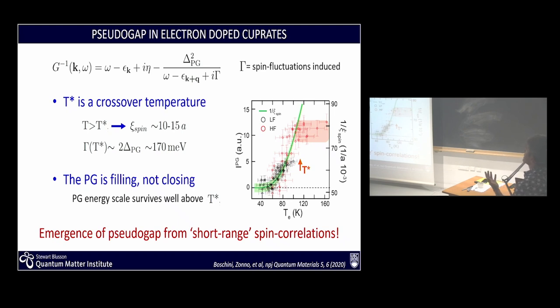We can also fit, as we did before, the photoemission intensity using a spectral function, or a Green's function, which instead of a superconducting gap has a term which refers to spin fluctuation. This is the gamma now. And delta is now not a superconducting gap, but a pseudo gap. So we can do pretty much the same job as before. What we see is that we can reproduce the spectral function well when we keep the pseudo gap value constant, and much of the action is instead in the lifetime. Once again, the lifetime is the key feature.